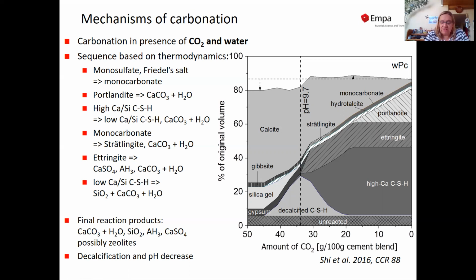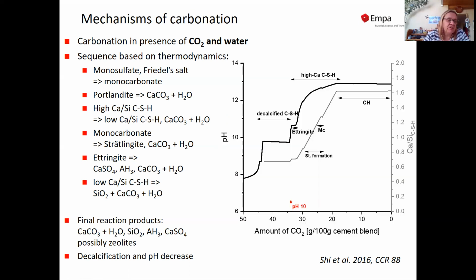However, we do not only change the composition of the solid phase, we also calculate a decrease of the pH, which is shown here in the black line, as well as the decalcification of the CSH, given here in the gray line, until we end up at the low calcium to silica CSH, and later this will be destabilized to silica.